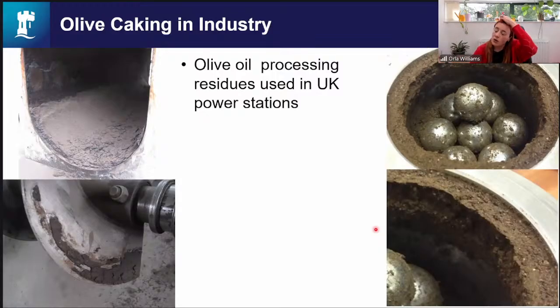One of the other things we've been looking at as well is industrial issues. What we have here on the left is a screw feeder from EDF Cottam, where they were trialing co-milling olive cake. Olive cake, as I mentioned before, is a residue from olive oil pressing. As it was going through the screw feeders, it was forming this solid cake, and they were having to use jackhammers to get it out. It was like concrete, and they were having to replace the screw feeds on a very regular basis. And as you can imagine, that's not economically sustainable.